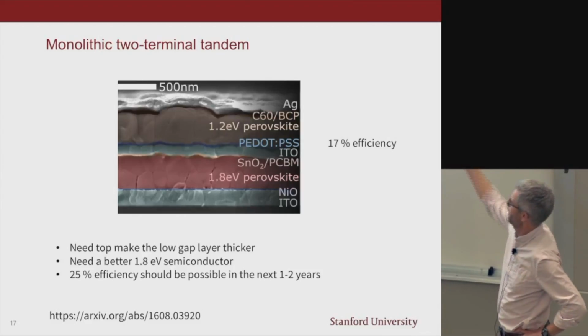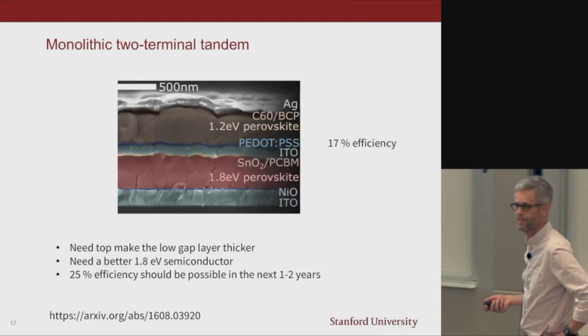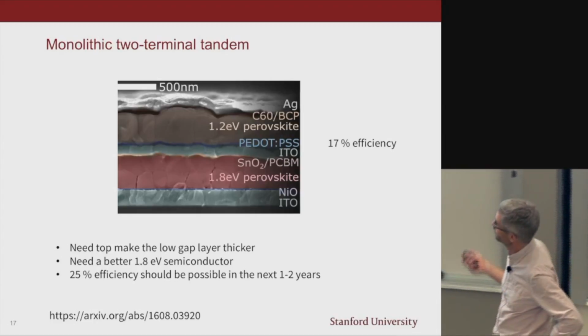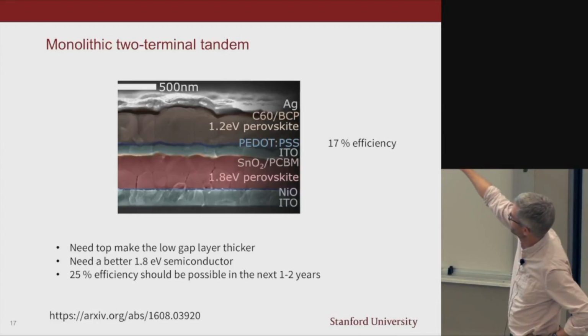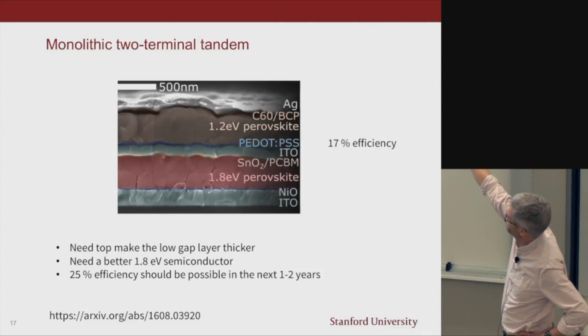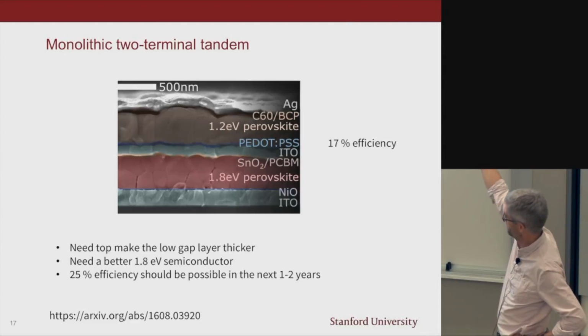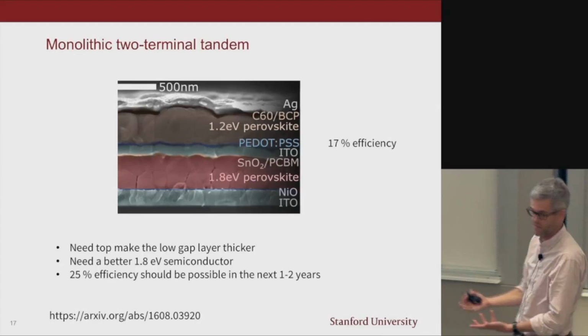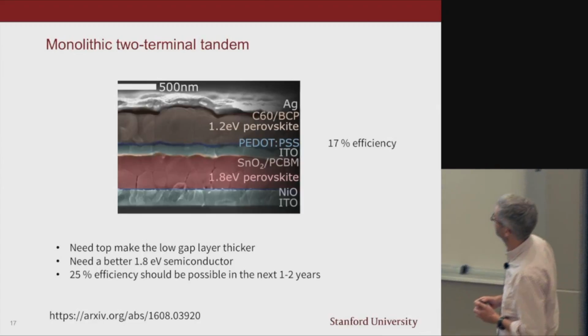The layer is just not thick enough. It's not absorbing the light. That's an easy one to solve, and we don't quite have the right band gap here. You have to get the band gaps just right because you need the same current in both solar cells. If one puts out less current than the other, it pulls the stack down.